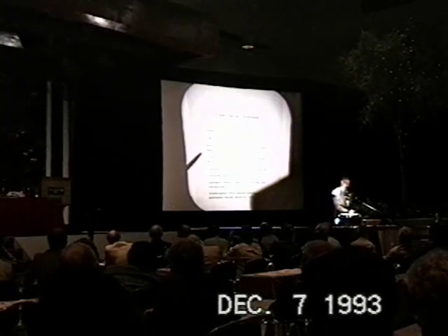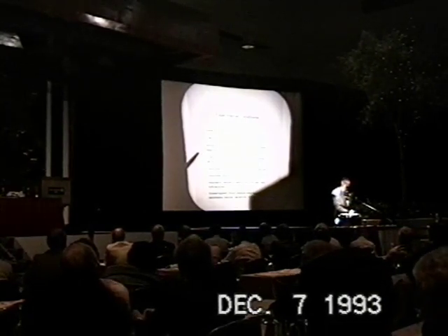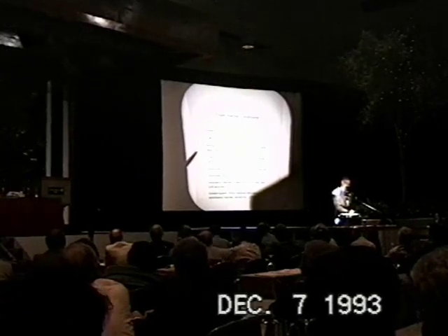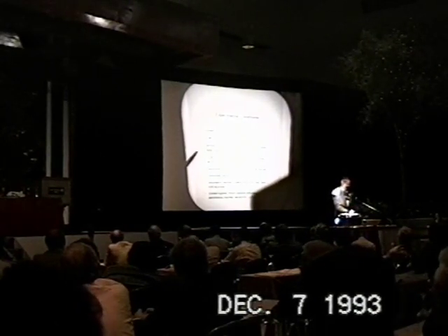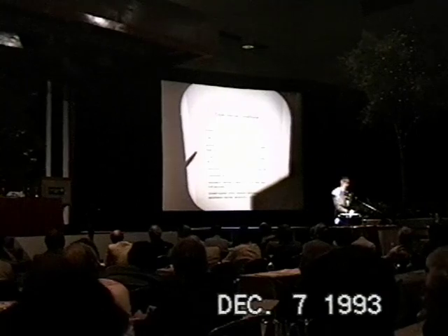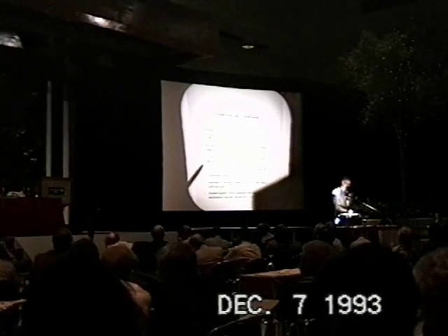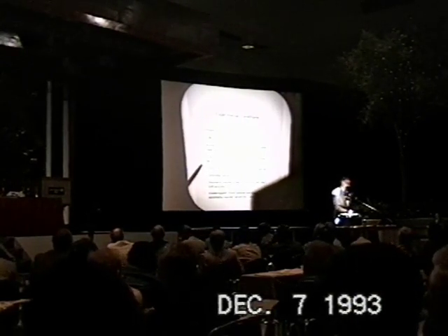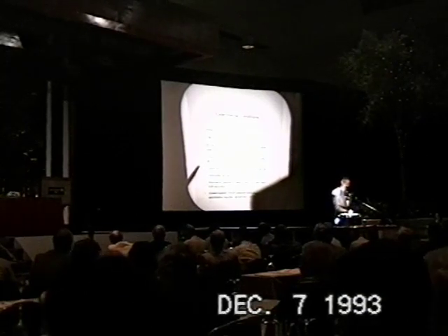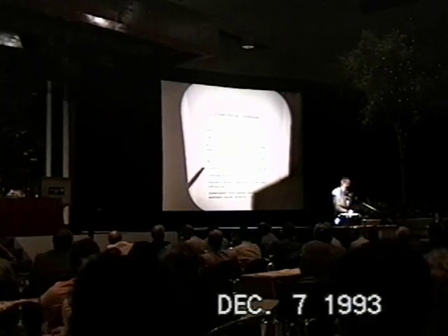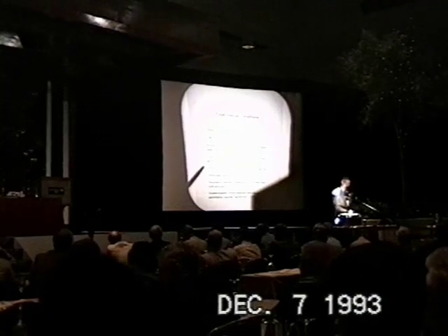However, there was a rubber septum that allowed us to withdraw electrolyte samples into one single cell. In one cell out of four we did this kind of electrolyte sampling, whereas the cells remained untouched in the three other cases. In the study reported on here today, we were using 2 millimeter diameter electrodes of typically 2 centimeter length, manufactured by Hoover and Strong, with a rather modest commercial type of purity, namely 99.9%.